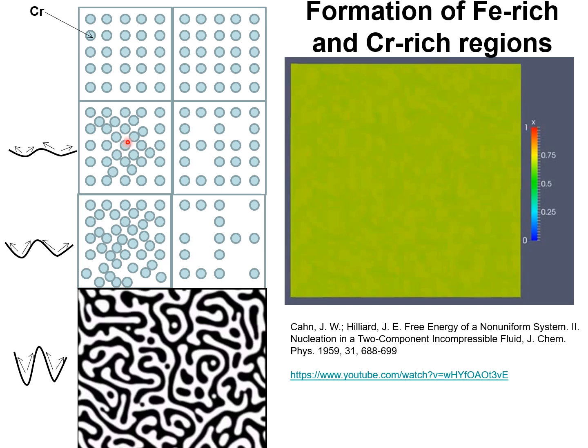Since the Fick diffusivity is negative in this region, this leads to a situation where the diffusion will be up the atom fraction gradient of chromium, and this would lead to an exacerbation of the segregation phenomena with more chromium atoms migrating from the right compartment to the left compartment. So this is a self-accelerating process where uphill diffusion will increase the segregation of chromium in the left compartment and lead to an excess in the atom fraction of iron in the right compartment.